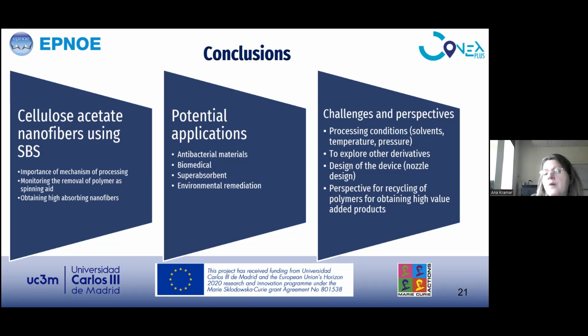the objective of further study. However, there are still challenges and many perspectives in this area, in that we should investigate more the processing conditions to explore other derivatives. I only showed cellulose acetate today, but we can probably process other cellulose derivatives. I know that it is also possible to process pure cellulose. One group from Sweden, I believe in 2019 or 2020, processed pure cellulose from ionic liquid using solution blow spinning, and their submicrometric fibers were around, I believe, 1-2 micrometers in diameter, so thicker than in our case, but still they showed that it is possible to process pure cellulose.